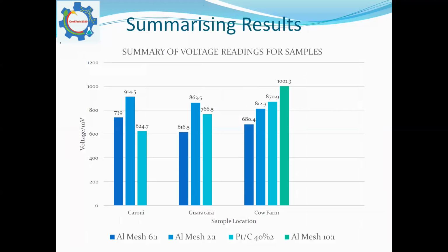We gather from the results that a larger anode to cathode ratio can generate a larger voltage, but not for long periods, while smaller ratios saw less fluctuations. The material plays a role in the stability where platinum carbon electrodes maintain more stable voltages. From the graphs, we can see that animal waste is the most efficient power source in our study.